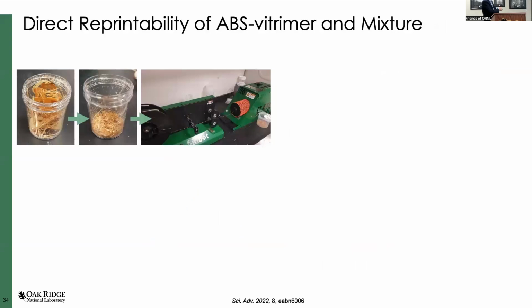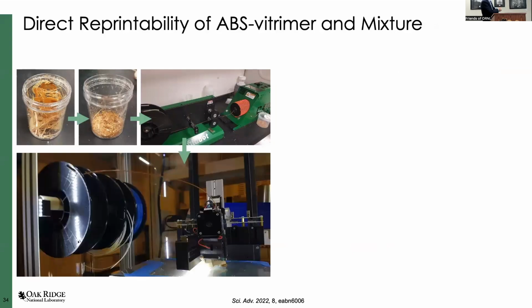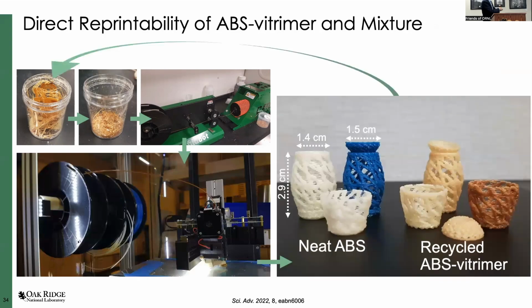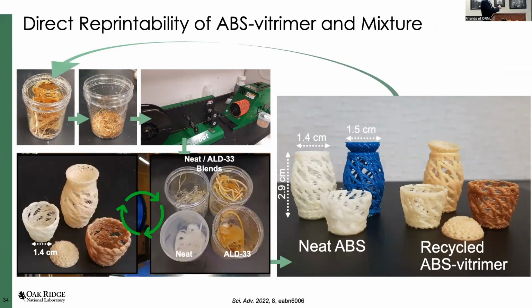But the interesting part is we can print many times. We grind it and we can print, even blended. You can see the neat material doesn't have a color, and you can see it's a little bit blended. You can print many times. This is still one of the only materials you can print many times with this kind of chemistry we have. So that's quite a unique material.